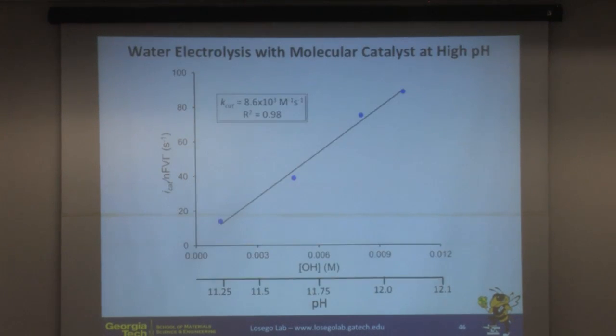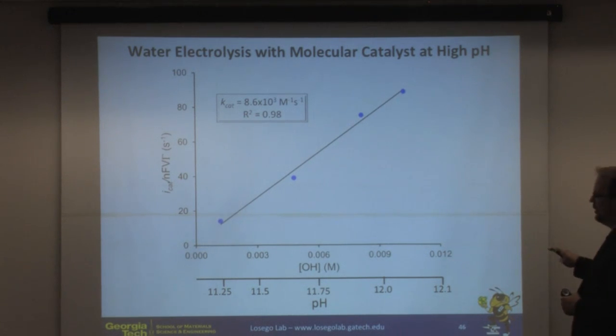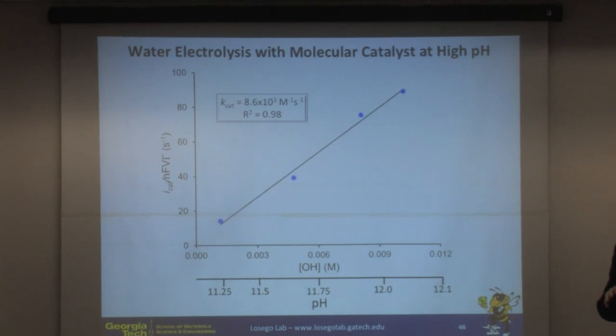Okay, and so what that allows us to do is increase reaction kinetics by a couple orders of magnitude. This is actually 100 to 1,000 times faster than the processes that occur at the lowest pHs. And prior to us demonstrating this, the only reactions they could run were at pHs less than 5, because the molecules just don't adhere to the surface except at those lowest pHs.